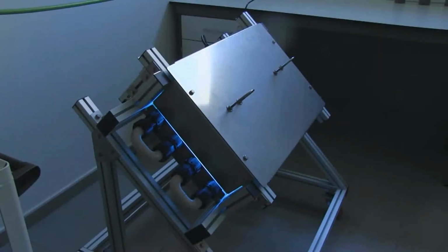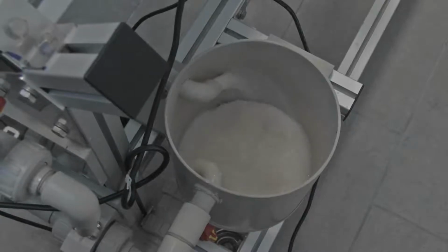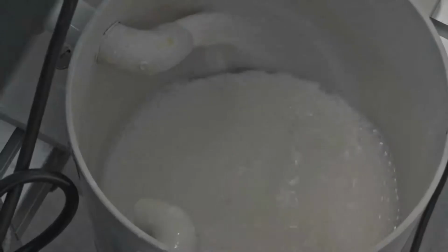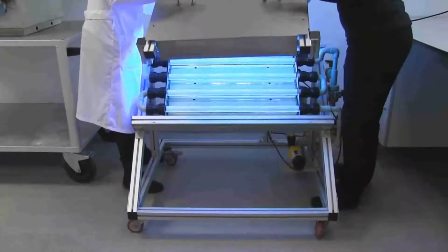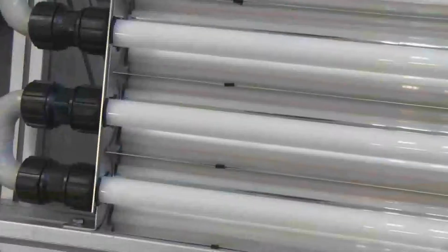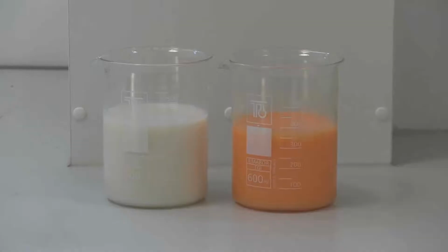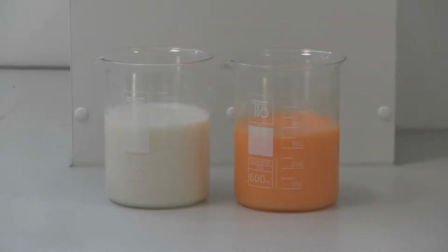As a photocatalyst, titanium oxide nanoparticles have been used, which can be incorporated directly into the water and circulate through the reactor. To perform the photocatalysis, a photoreactor has been employed, consisting of a panel with some tubes through which contaminated water circulates. It can be observed that the process can eliminate more than 90% of colour from the solution in 90 minutes and 75% of the pollution load.